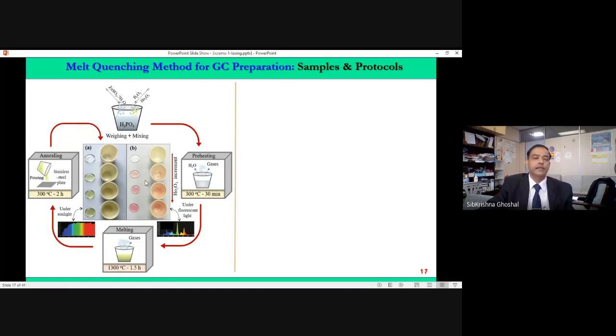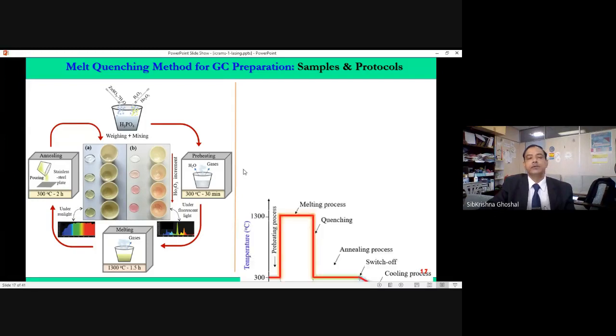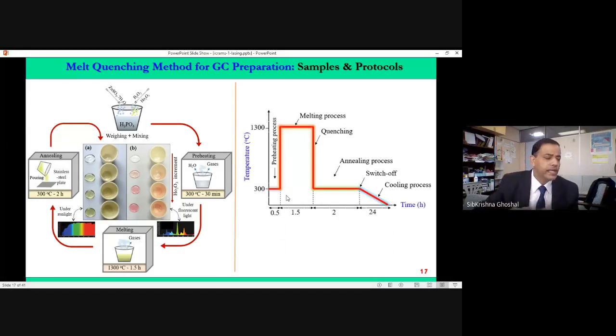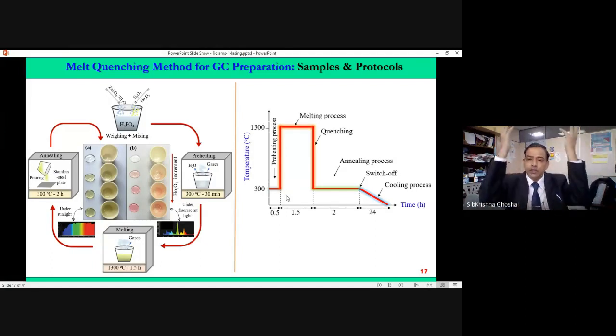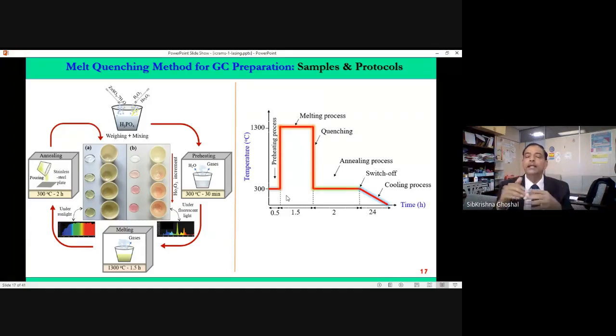Right hand side is showing the material with rare earth doping. That's why the color change, and this is the way we get. So heating and cooling schedule, that means at what temperature we heat, shock heat, then we quickly quench, that means very fast we cool down, then again slowly heat, then anneal, then we cool finally to room temperature. This temperature schedule is very, very important to get the right crystallinity.